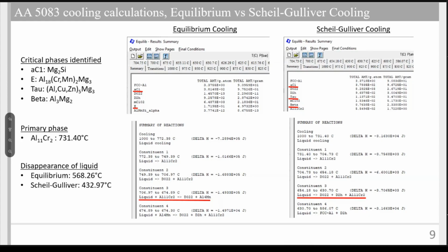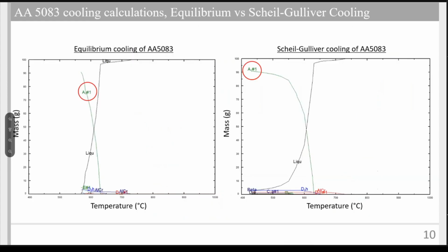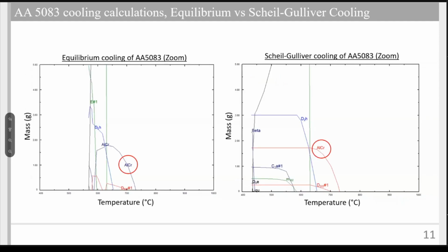Now, all these results are much easier to visualize if you do a plot. Here you have a comparison between the two modes of cooling, where you can see the final disappearance of liquid being much lower for the non-equilibrium cooling. You can see, of course, that the main phase precipitated is the Al matrix, but at the bottom you will have the other intermetallic phases. So if we apply a zoom on them, we can see the effect of the cooling rate on the phase formation.